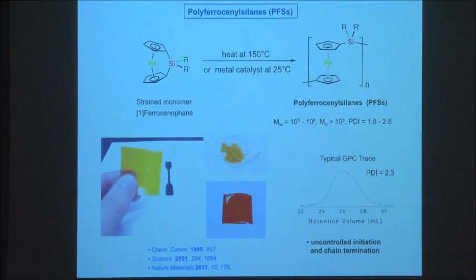We initially made them by simply taking these monomers and heating them, or using metal catalyst at room temperature, and you can make these polymers. It's a high molecular weight material. If you look at the molecular weight distribution by gel permeation chromatography, you get a broad distribution. And the reason for this is these polymerizations, even though you get high molecular weight products, you get a range of chain lengths because there's spontaneous chain termination that occurs during the polymerization. So these monomers will open and then they start joining together, but you get a random termination step which can occur at any chain length. And so you get a range of chain lengths here, which you see in this distribution.